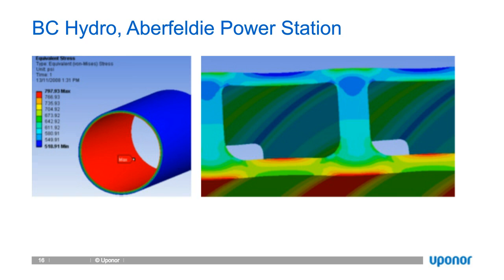The FEA of a polyethylene DR11 pipe, picture on the left, indicates a stress distribution of about 520 psi at the OD and approximately 800 psi at the ID of the pipe. So there's about a 50% greater stress at the ID than there is at the OD of the pipe. The stresses, however, in the profile wall polyethylene pipe have a greater range of stresses. It's not just a distribution range of 50%. It's considerably higher than that.